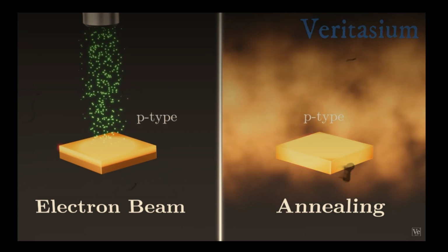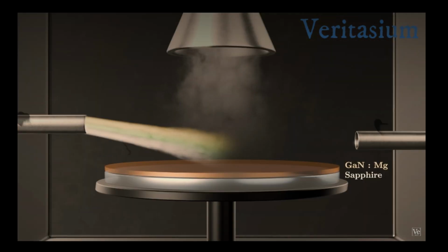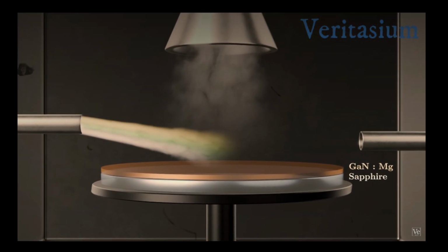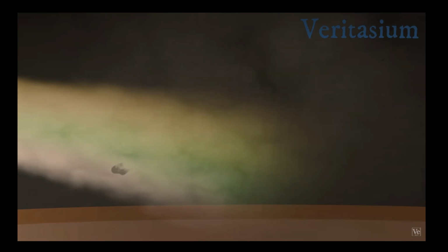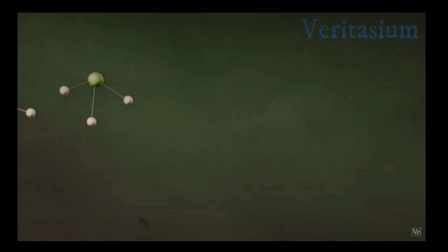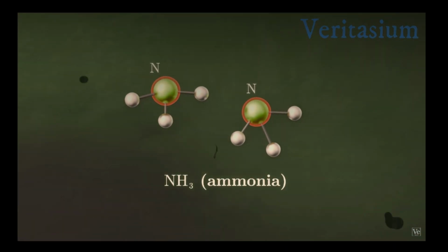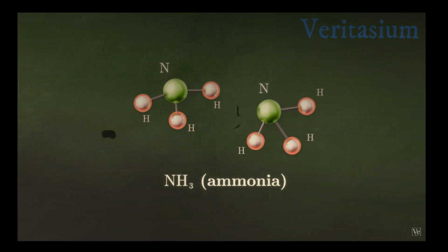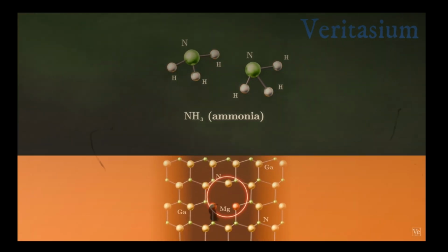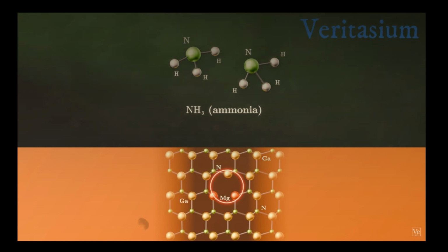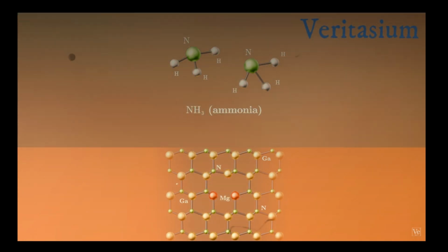His work also revealed why the P-type had been so difficult. To make gallium nitride with MOCVD, you supply the nitrogen from ammonia, but ammonia also contains hydrogen. Where there should have been holes in the magnesium-doped gallium nitride, these hydrogen atoms were sneaking in and bonding with the magnesium, plugging all the holes. Adding energy to the system released the hydrogen from the material, freeing up the holes again.